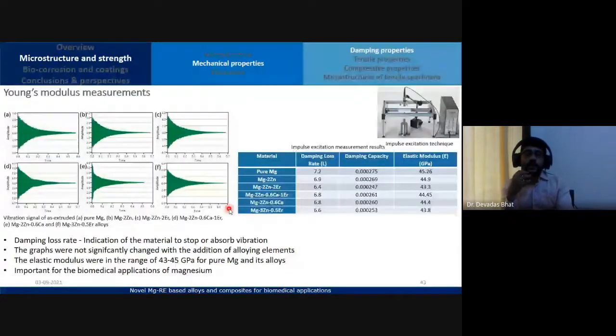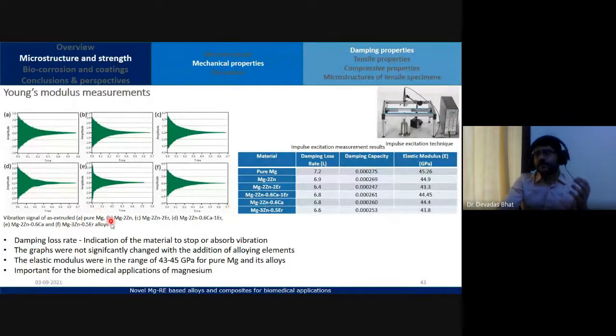Here is one technique by which you can calculate the Young's modulus, called the damping method, or the impulse excitation technique. You take a sample, place it on the equipment on some wires, and then you use a tuning fork and introduce a certain vibrational frequency into the material. Because of the excitation, you get a vibrational signal from the material which you can plot as a function of time, amplitude versus time, and then you can calculate the elastic modulus using the damping loss rate.